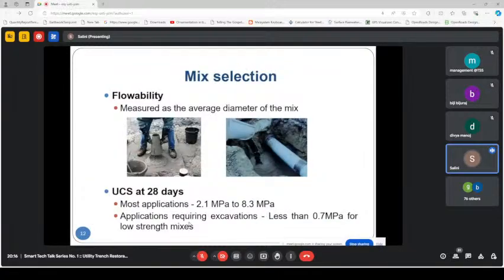So the mix selection depends on two criteria. One is the flowability, that when placing the mix, it should flow and fill the voids, and then the UCS. For most applications, that strength is between 2.1 MPa and 8.3 MPa, and for excavations, like when we need to access the utility at some later stage, we should make sure that the long-term strength is less than 0.7 MPa if you want to excavate manually. But if you have some machinery like a backhoe, you can excavate up to 2.1 MPa. Beyond that, it is very difficult to excavate, and it may even damage your utility.